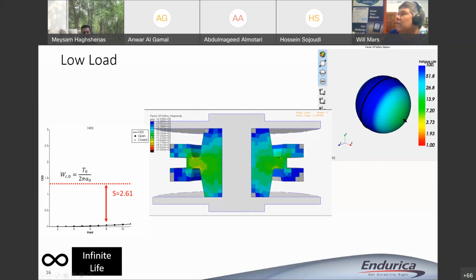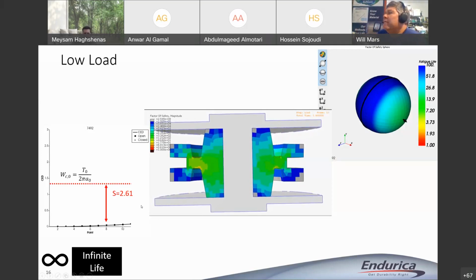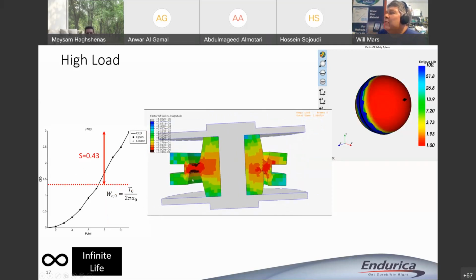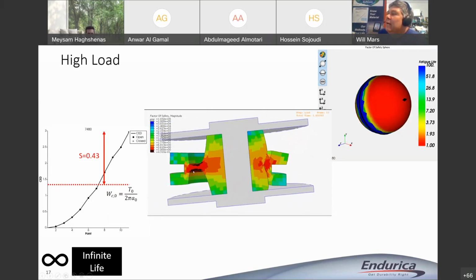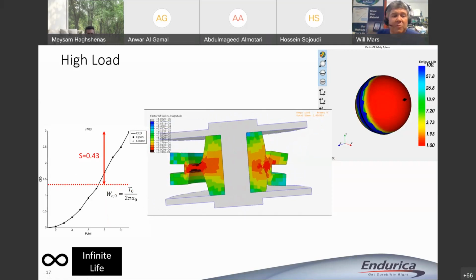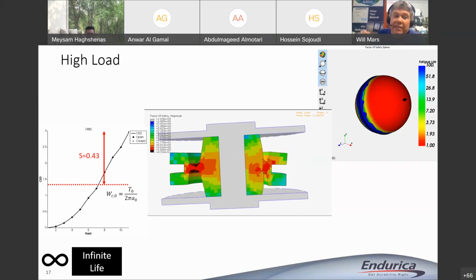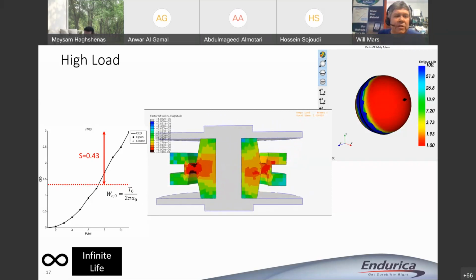In this case, under the low load, the worst element happens to end up with a safety factor of about 2.6. So we're going to have infinite life with a margin of about 2.6 relative to the life limit. If I repeat the analysis for the high load case, now you can see I've jumped over the fatigue limit, and I've got a couple of elements here that are colored black, and those elements have a safety factor of 0.43. So this doesn't mean that the part has failed instantly, but it does mean that the life will not be infinite. And this does not tell you how long the part will live. If we see the black elements, that means maybe we need to do the safe life approach, or redesign the loads or the part or something.